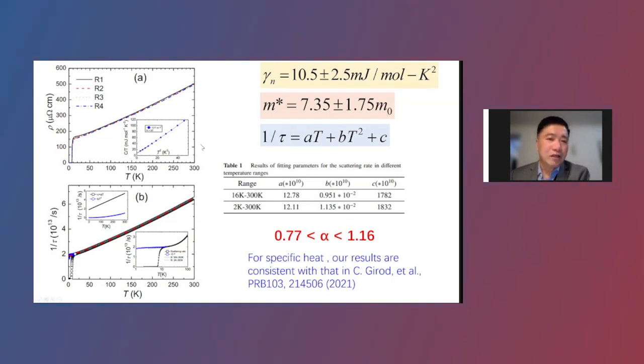And then we use this formula to fit the resistivity data down to low temperature. We found that the contribution is mainly contributed by a linear term. So here, after the fitting, we use the parameters to calculate the data. The blue one is given by this quadratic term, and the black one is given by the linear term. So the linear term dominates here, okay?